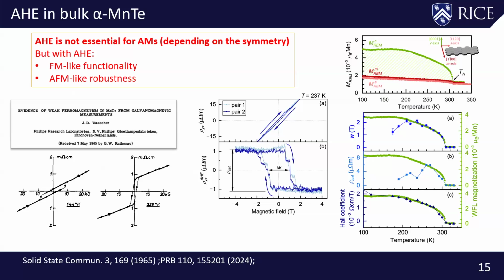When Shijie and Zhao Yu started doing this in the group, they grew these manganese tellurium samples, and they couldn't reproduce this anomalous Hall effect. In fact, manganese tellurium is not really a good metal. It's actually what we call a semiconductor. So they had to look at various different samples. Oh, this anomalous Hall, by the way, only appears in a very narrow temperature regime below Tn.